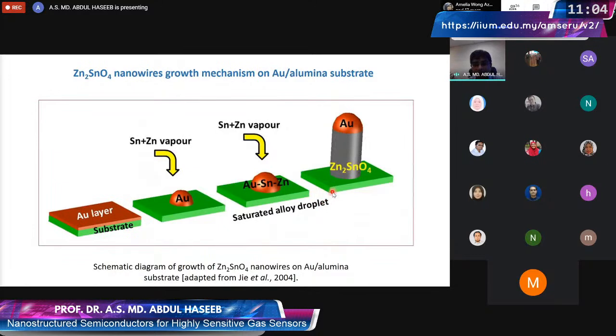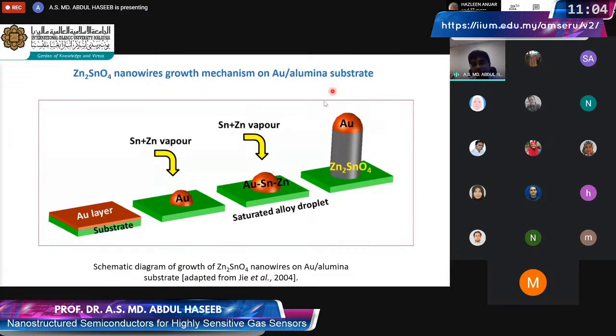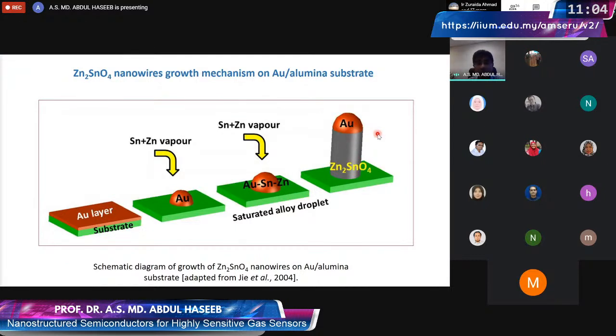and this is called the vapor-liquid-solid mechanism, where the tin vapor will dissolve in gold, and gold is formed at high temperature from the layer that we used, and then once they get saturated, the zinc and tin tend to deposit, and by having oxygen in the surroundings, they get oxidized, and the gold cap remains as the oxide grows, and we saw gold cap also on the surface, on the top end of the nanowires.